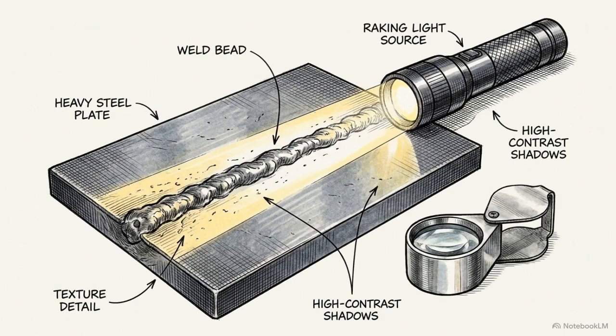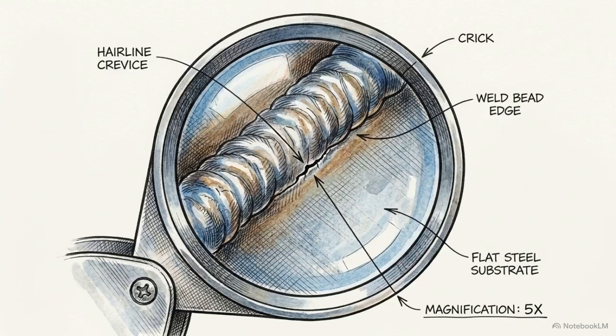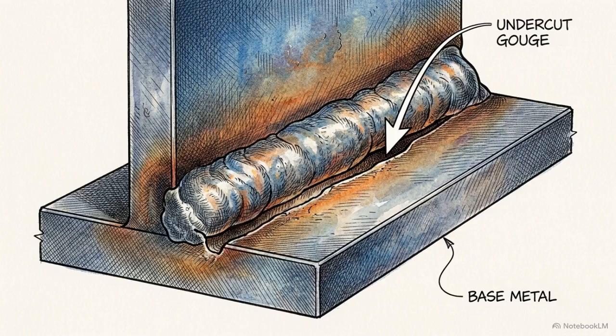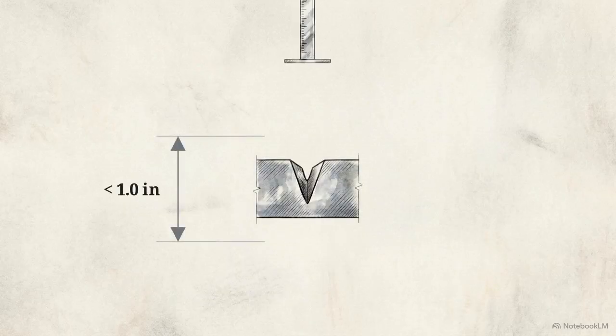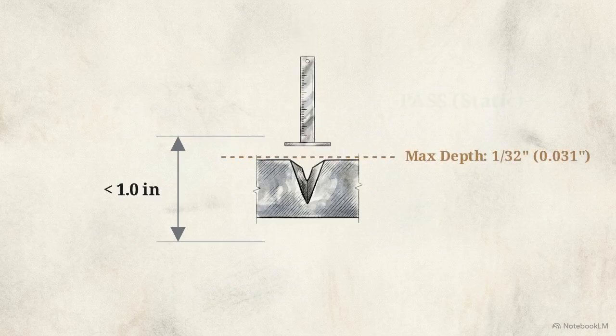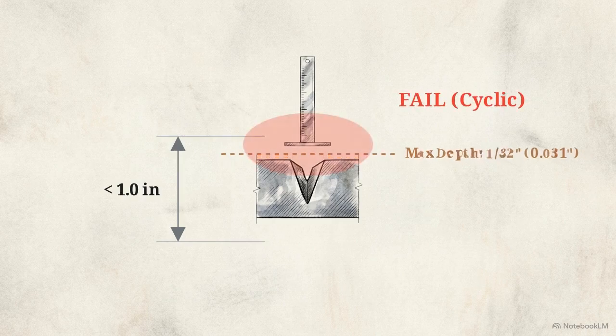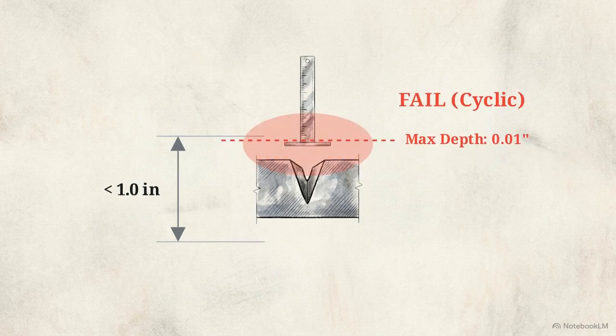Next, we hunt for surface anomalies by shining a raking light source across the joint, and using a 5x magnifier, you can spot microscopic defects hiding along the weld toes. One of the most common issues is undercut, a groove melted into the base metal. For materials under 1 inch thick, the maximum allowable depth for an undercut is 1/32 of an inch. Under cyclic loading, the allowable undercut limit shrinks to 0.01 inches to prevent fatigue failure.